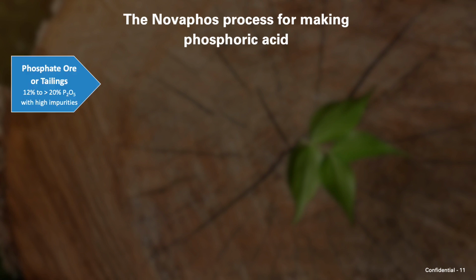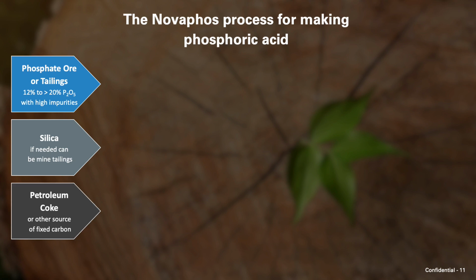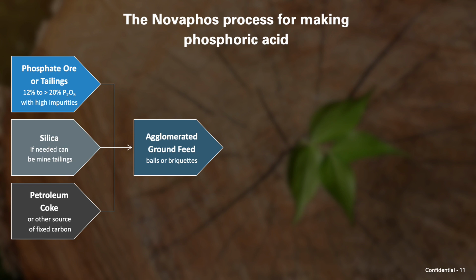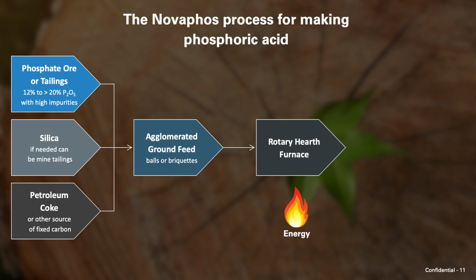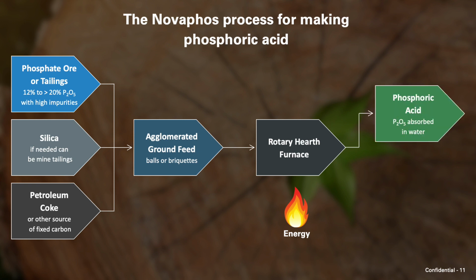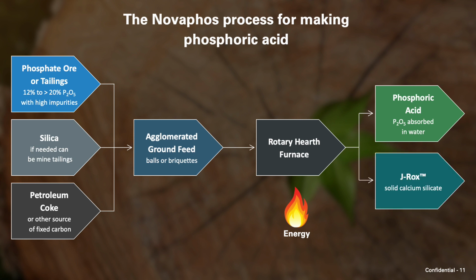Here's the Novaphos process for making phosphoric acid. We start with low-grade phosphate rock or even mine tailings. And this can be at 12 to 20% P2O5 and contain a lot of impurities. We add some silica if needed, although a lot of low-grade phosphates already contain enough silica. And then we add a source of carbon, which participates in the phosphate reduction reaction. We grind, dry, and agglomerate this feed material, which then goes into a rotary hearth furnace where the reduction reaction takes place. The resulting phosphate gas is absorbed in water to make a phosphoric acid, and the processed feed material exits the furnace as a useful solid calcium silicate product that we call J-Rox™.